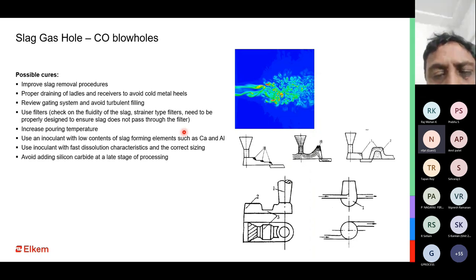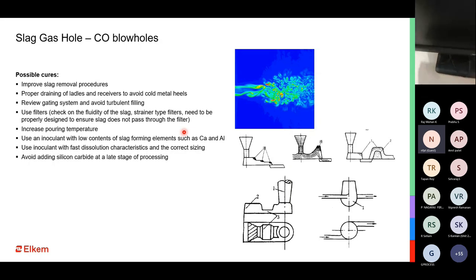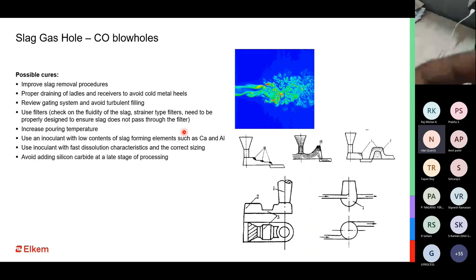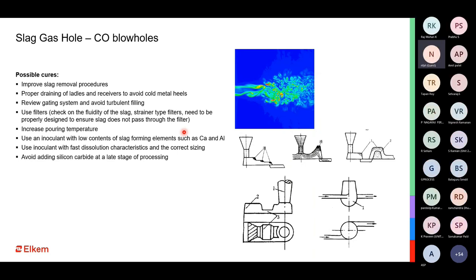In case of ductile iron, it becomes even more important to use the most suitable kind of filters, because these filters need to be designed in such a manner that any kind of slag, be it liquid slag or the solid ones, should not pass through the filters. We have to make sure that the metal treatment alloys that we use, be it ferrosilicon, magnesium or inoculant, are of such a composition that you do not have excess slag contributing elements in them.